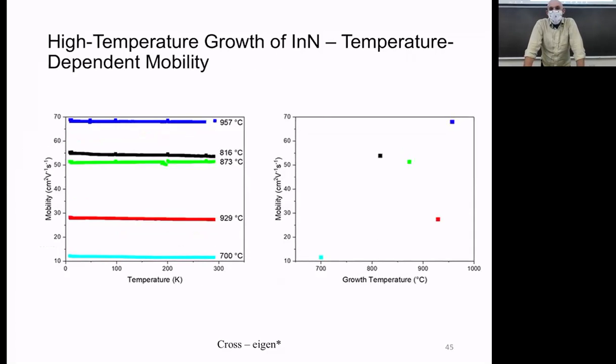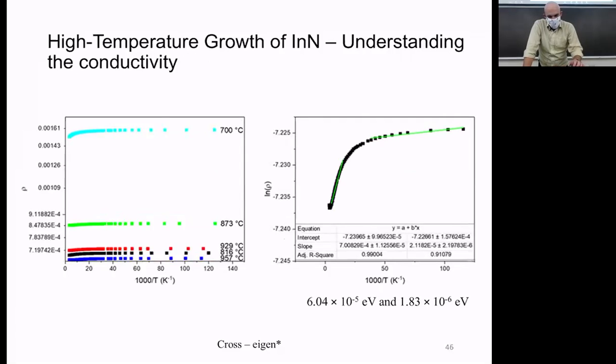I look at the mobility of these electrons, and the mobility is really, really low. I'm expecting values sitting above the hundreds, preferably. Predicted values are sitting at 20,000 for this material. So there is definitely a problem with my material. And I expected that. It's not flat, right? So what do I need to do?